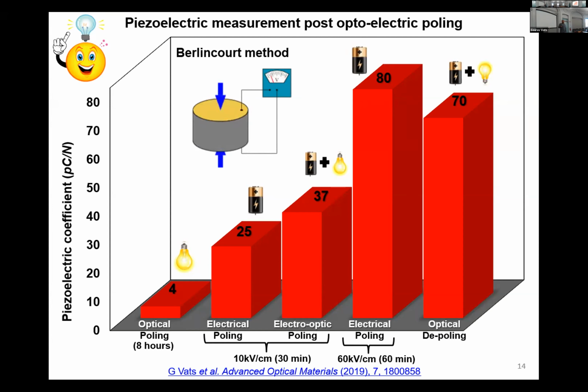Then we did electrical poling. The sample was fully poled in one direction, and we shone light in the opposite direction, and we could actually depole the sample as well. So here we are showing that we can actually pole and depole a sample with light exposure.